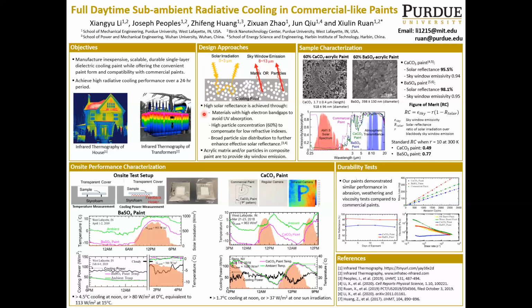In this work, we use three approaches to enhance the overall solar reflectance. First, we chose dielectric materials with high electron band gaps, such as calcite and barium sulfate, to avoid UV absorption. However, these materials often suffer from low refractive index, so particles are added at a high volume concentration at 60%. Furthermore, we adopt a broad particle size distribution rather than a single particle size, which further increases the overall solar reflectance at the same concentration.